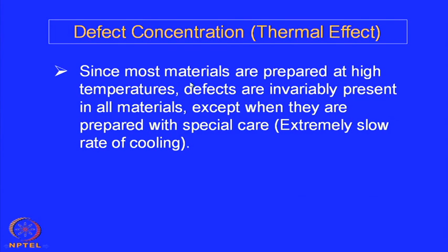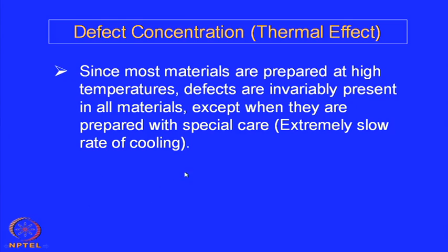Since most materials are prepared at high temperature, defects are invariably present in all materials, except when they are prepared with special care, such as an extremely slow rate of cooling. If somebody wants a very pure material, or not only pure but defect-free material, then special care has to be taken so that defects are not generated. But under normal circumstances defects will be generated, and they actually tend to minimize the free energy of the system, and minimization of free energy means it is more stable thermodynamically.